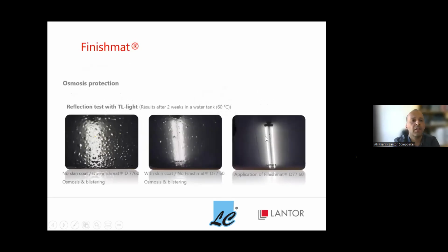So as an example, for osmosis protection of the laminate using finish mat, we have made 3 glass polyester resin laminates. This one is without skin coat and without finish mat. This one is with skin coat but without finish mat, and this is with finish mat. And we have placed these laminates for 2 weeks in a water tank at 60 degrees, and we have studied the osmosis effect. You see here a lot of blisters happening, here a little bit less. And when you are using the finish mat, you see this surface without blister.